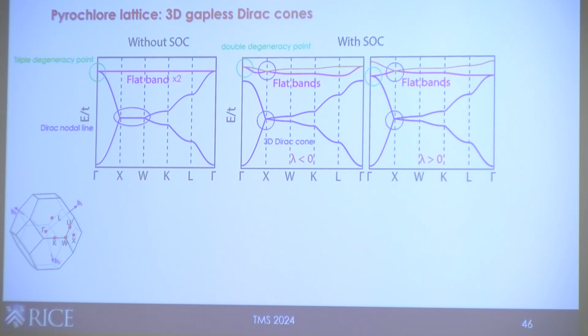The second thing that happens is that the spin-orbit coupling will also gap this Dirac nodal lines. It will gap it everywhere except strictly at the X point of the Brillouin zone. And what you notice is that actually every single band crossing, as long as your band crosses the X point, it will be a gapless 3D Dirac point. And this is something that's special for the pyrochlore lattice. And the reason for this is that there is an intrinsic non-symmorphic symmetry associated with the pyrochlore lattice. So how do you see that?